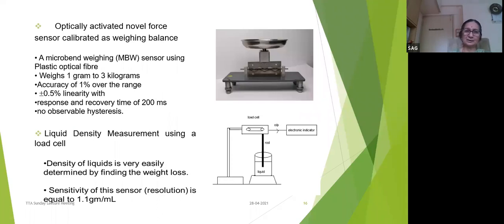We have developed a lot of sensors over these years. I'm giving you a few examples. This is an optically activated force sensor calibrated as a weighing balance, and a micro bending of the optical fiber is used. The pan is sitting on an optical fiber, wherein because of the weight of this pan, the optical fiber is bent. And bending will reduce the energy, or the light intensity, which is coming on the other side, the receiver side. And that intensity is calibrated in terms of weight.